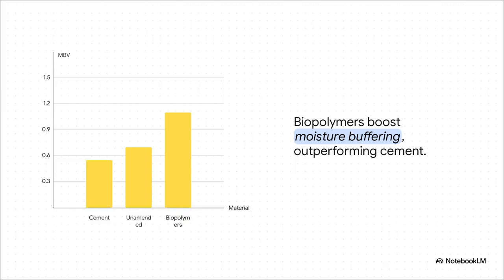So let's compare our materials against that villain we talked about: cement. Unamended soil has a baseline MBV of about 0.7. When you add cement to make the wall strong, the cement actually coats the clay particles and clogs the pores, dropping the MBV down to a dismal 0.55. But because biopolymer hydrogels have a natural inherent affinity for water, they don't just maintain the wall's breathability, they actually boost it. The biopolymer materials push the MBV up to between 1.0 and 1.15, shifting their classification from moderate up to good. So you get the strength of cement, but you also get a building that actively manages its own indoor air quality. That's a real win-win.